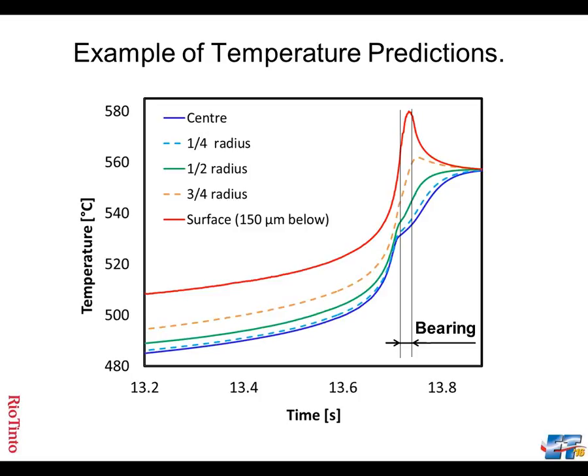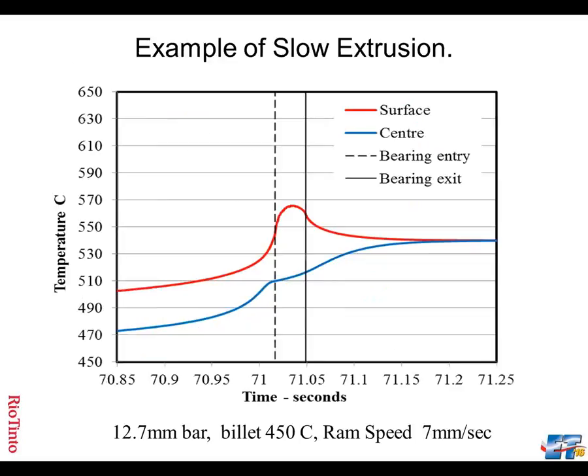And we have the plots at various positions through the thickness of the profile. What is really interesting with this is how fast the temperature drops between the surface and the core, and the material becomes more uniform in temperature. It drops to 560 Celsius, and this occurs within about 0.1 of a second. And I'll just show you a couple of illustrations of extremes.